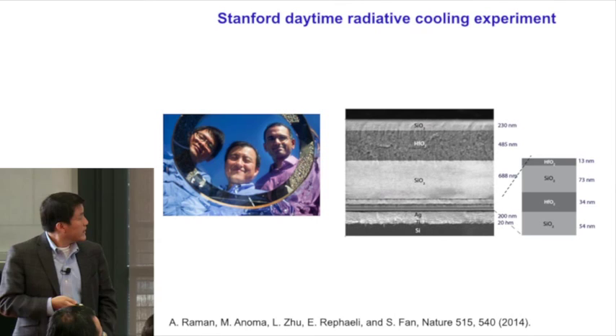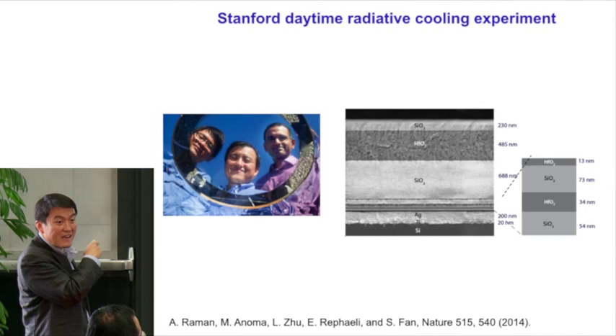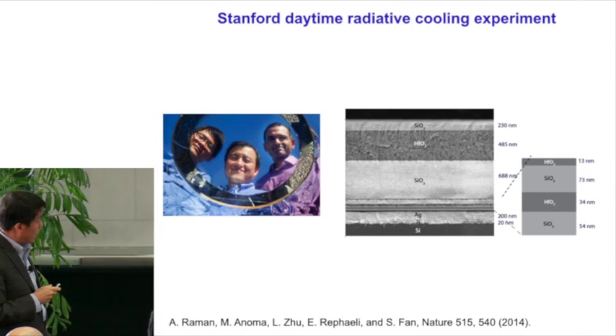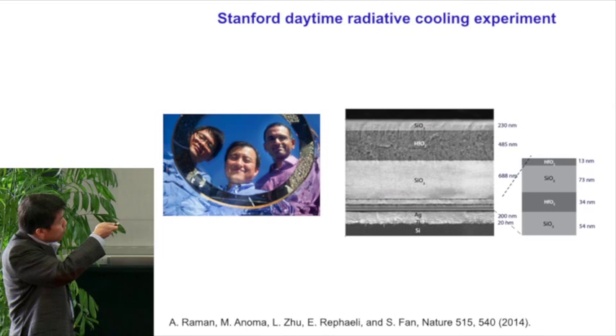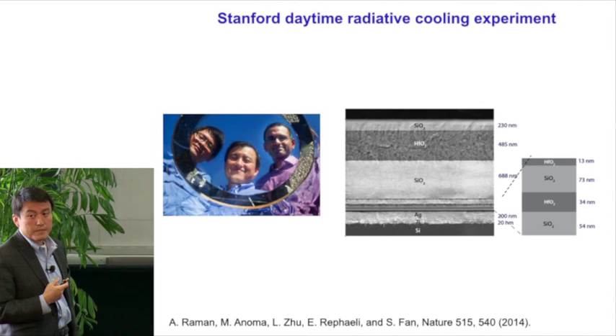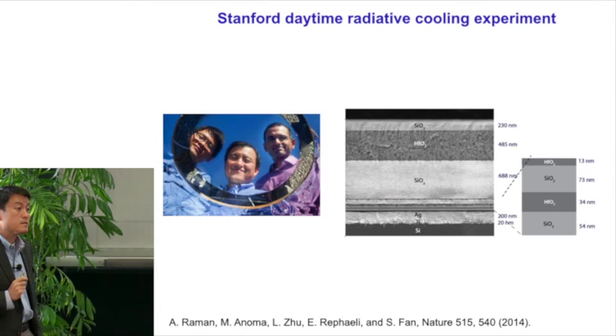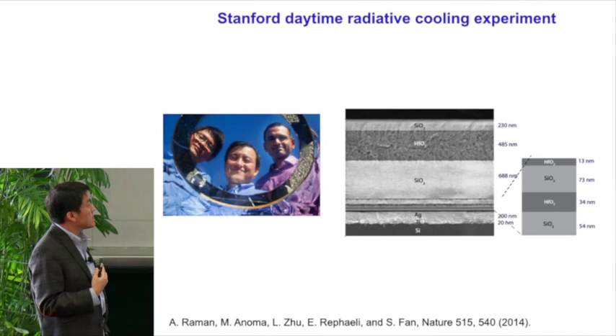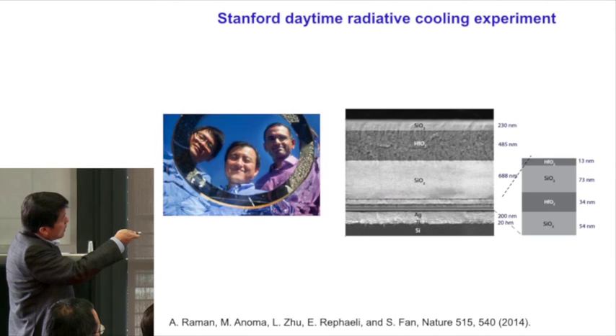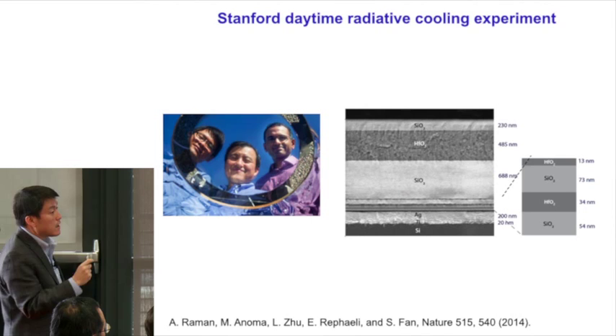So what we did is we made a structure on an 8-inch wafer. These are Aaswath Raman and Linxiao Zhu. Linxiao was sitting down there; they are some of the primary students and postdocs who did the work. These are 8-inch silicon wafers, and on the wafer we grow layers made of silicon dioxide and hafnium oxide. Silicon dioxide, as I mentioned, has a strong phonon-polariton response. Therefore, the top three layers, with thickness on the order of a few hundred nanometers, are used to radiate the heat out. The bottom four layers have thickness on the order of tens of nanometers. These, in combination with a silver layer, form a broadband mirror to reflect the sunlight.